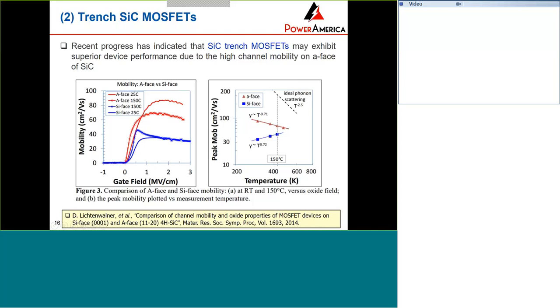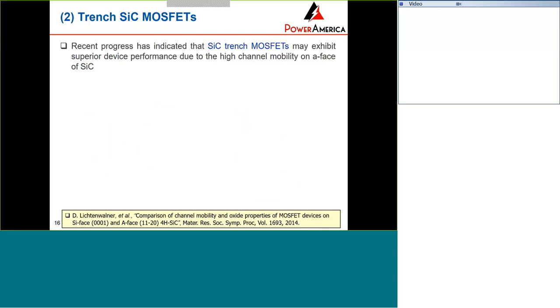So you can see that the mobility on the a-face is higher than the silicon face, and it also shows a different temperature coefficient. If you compare the peak mobility depending on the temperature, shown in the right figure, you will see that the silicon face mobility increases when the temperature increases, which agrees with the Coulomb scattering mechanism. On the contrary, the a-face mobility reduces with temperature, and it shows kind of an ideal phonon scattering mechanism. So they have different interface properties, and that property also affects the temperature coefficient.